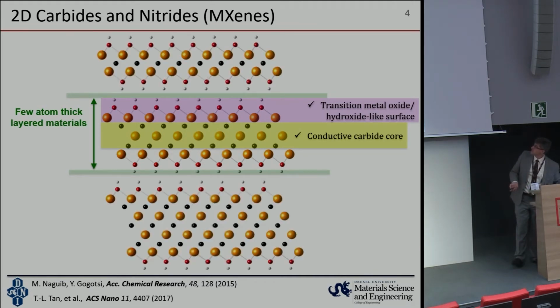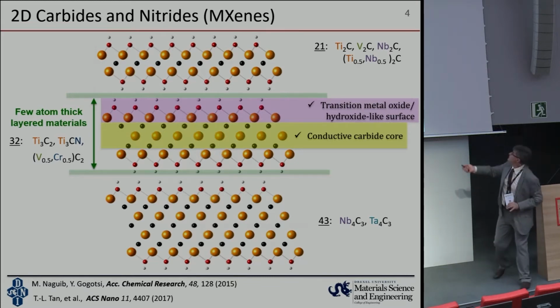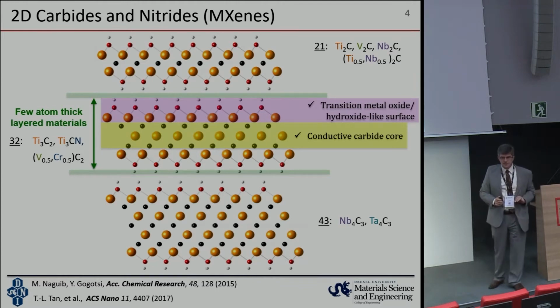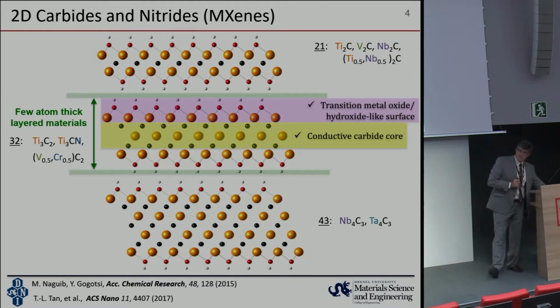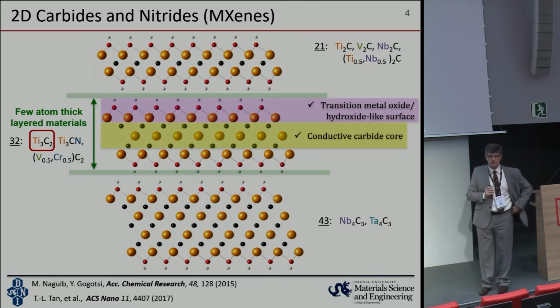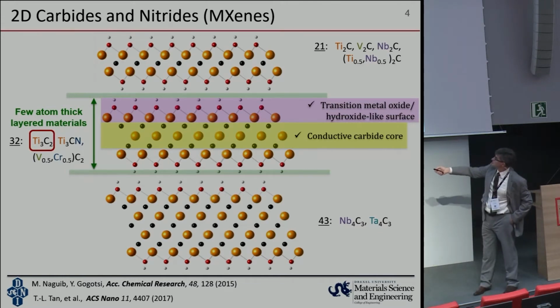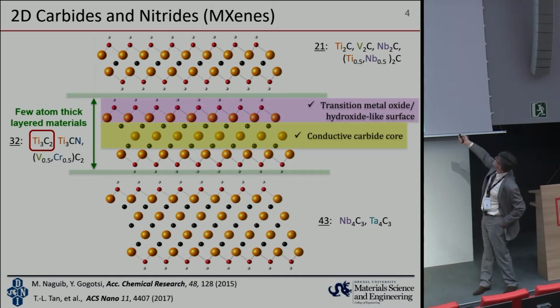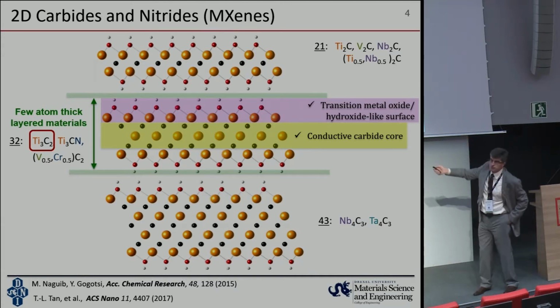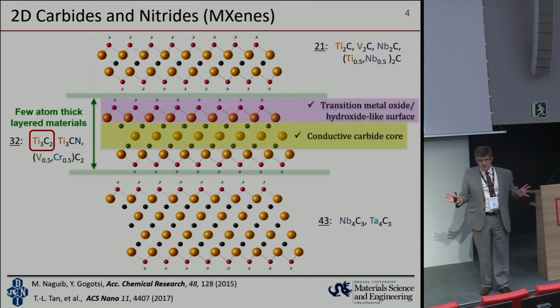Moreover, these materials come in 3 different flavors. We call them 2-1 structures, 2 layers of transition metal, 1 carbon or nitrogen; 3-2 structures, 3 layers of transition metal, 2 carbon or nitrogens; and 4-3. Within a year after discovery of the first one, which was titanium carbide, Ti3C2, we demonstrated all these 3 types of structures possible. Moreover, we showed solid solution on M side, solid solution on X side, carbonitrides here. Pretty much making it potentially the largest family of 2D materials available.